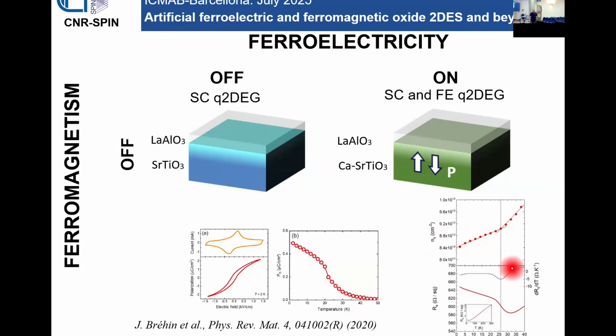And the coupling is demonstrated, for example, by looking at the sheet resistance as a function of temperature of the 2DEG, which shows at the ferroelectric transition a clear change in the slope. And then at low temperature, you can perform, for example, resistance versus gate voltage measurements, and you will find that essentially there is a ferroelectric loop with non-volatile change of the transport properties.